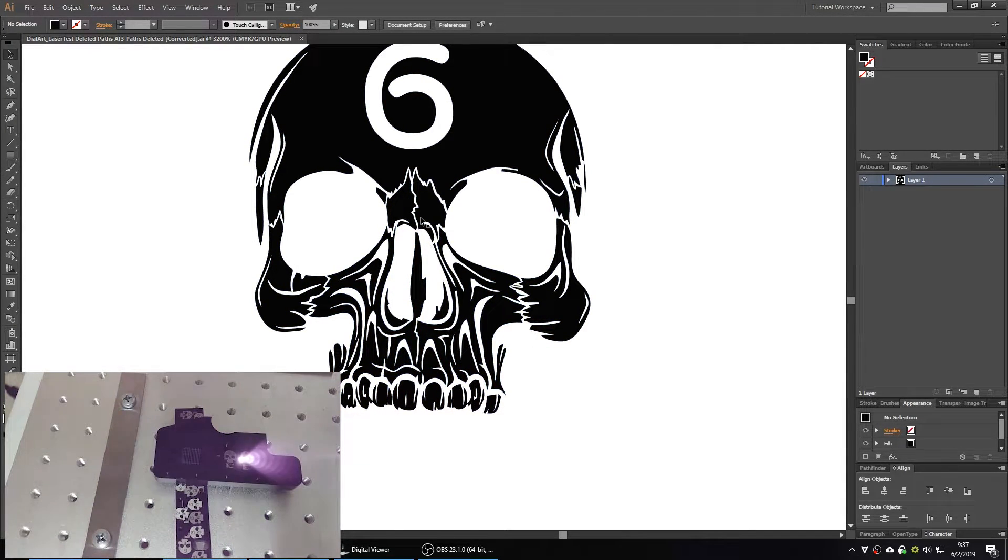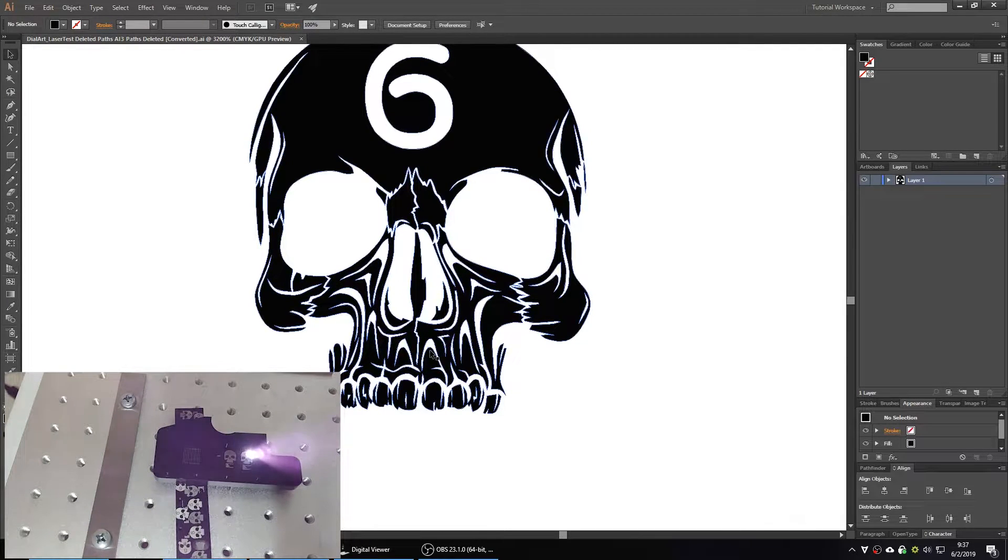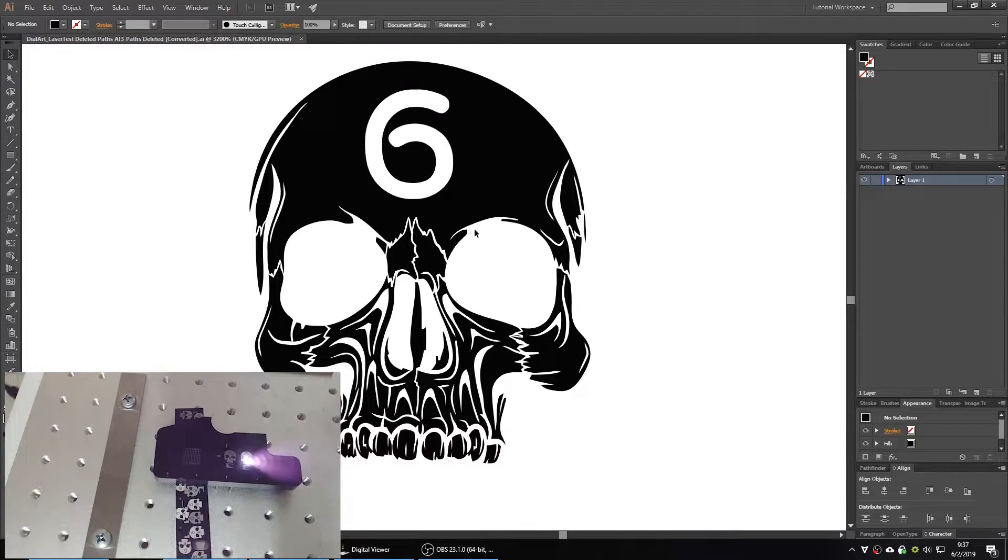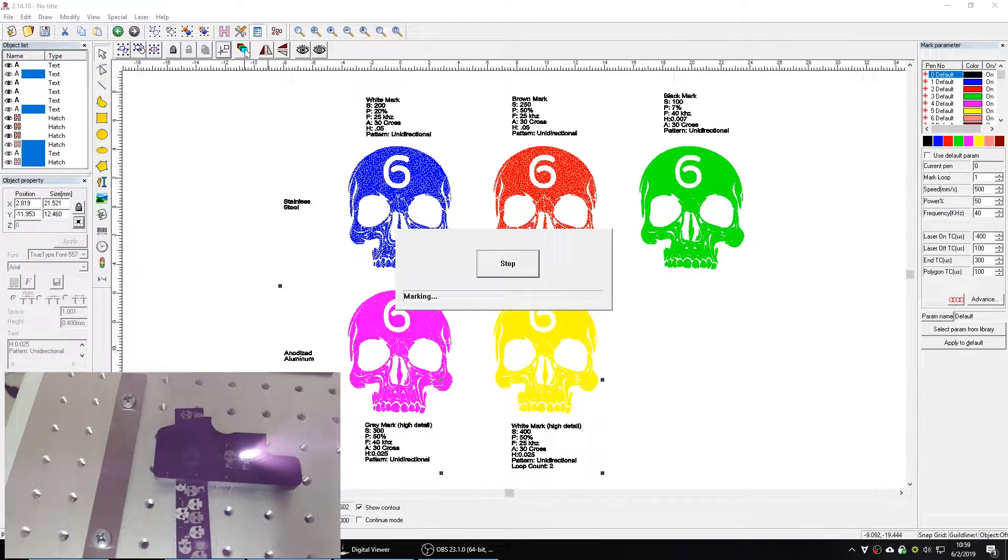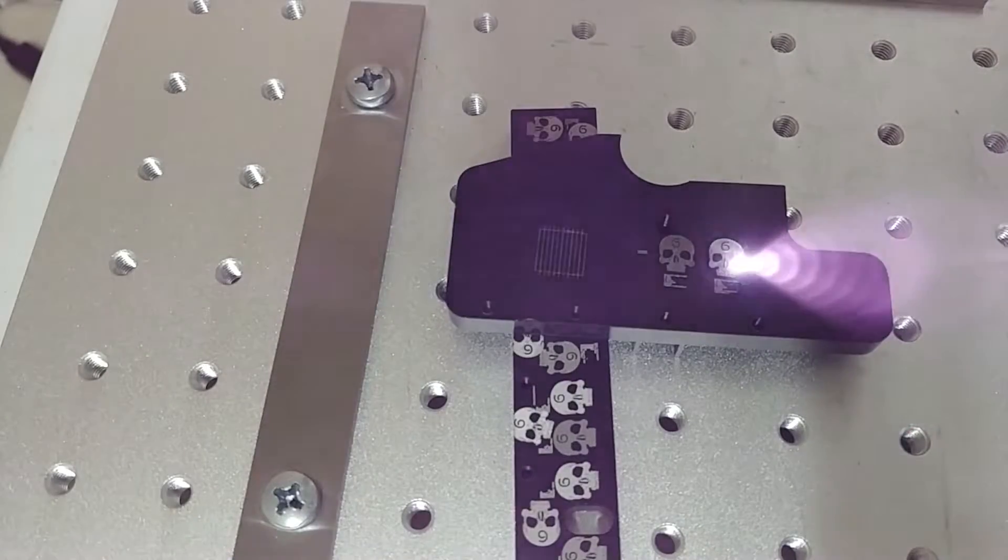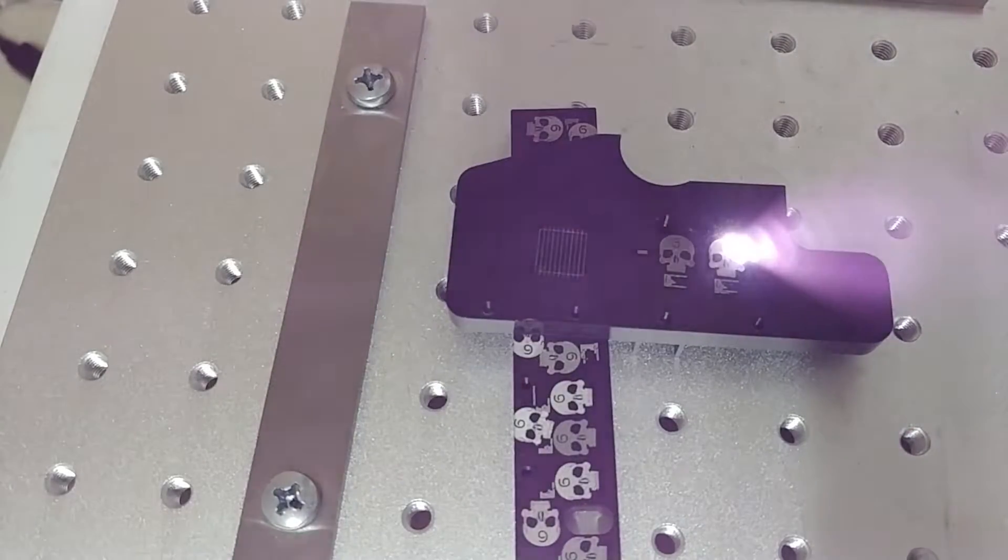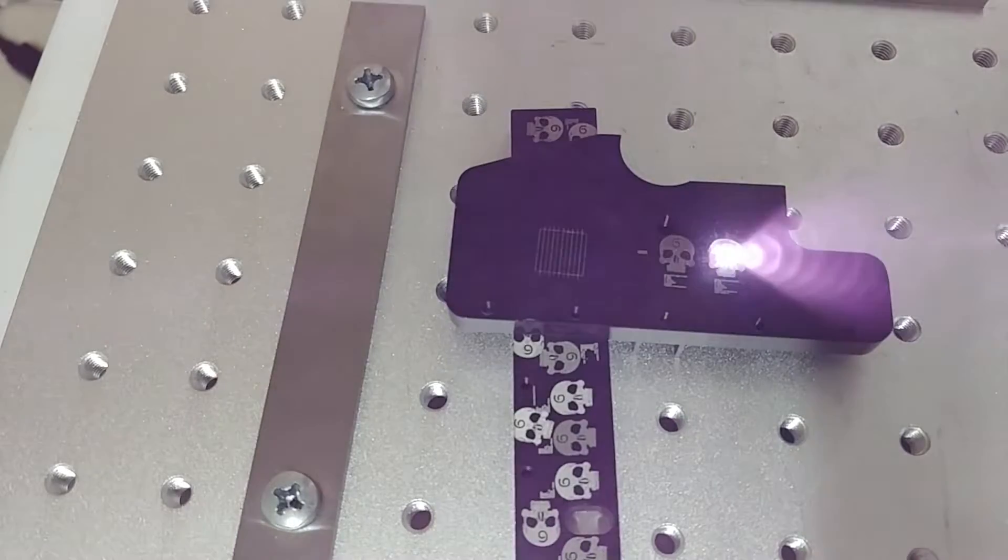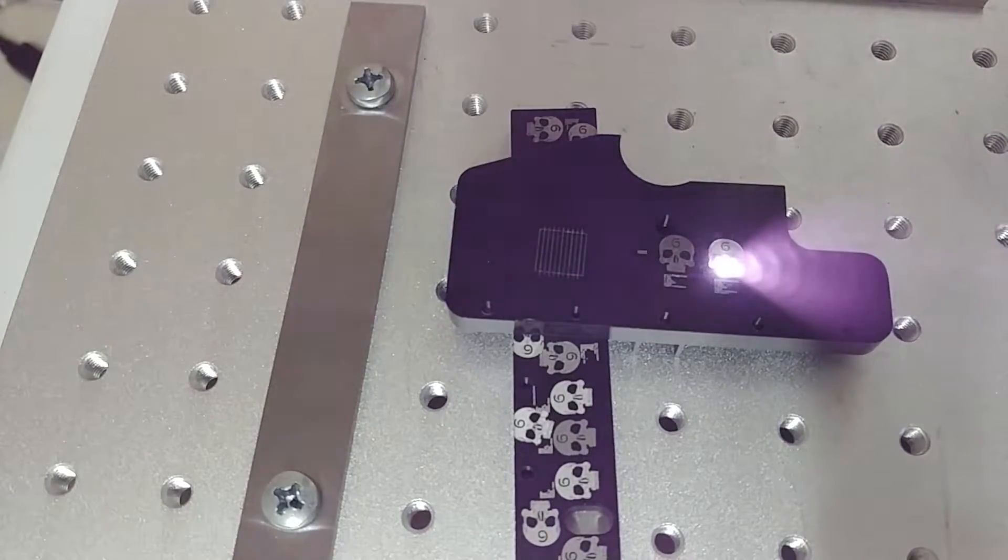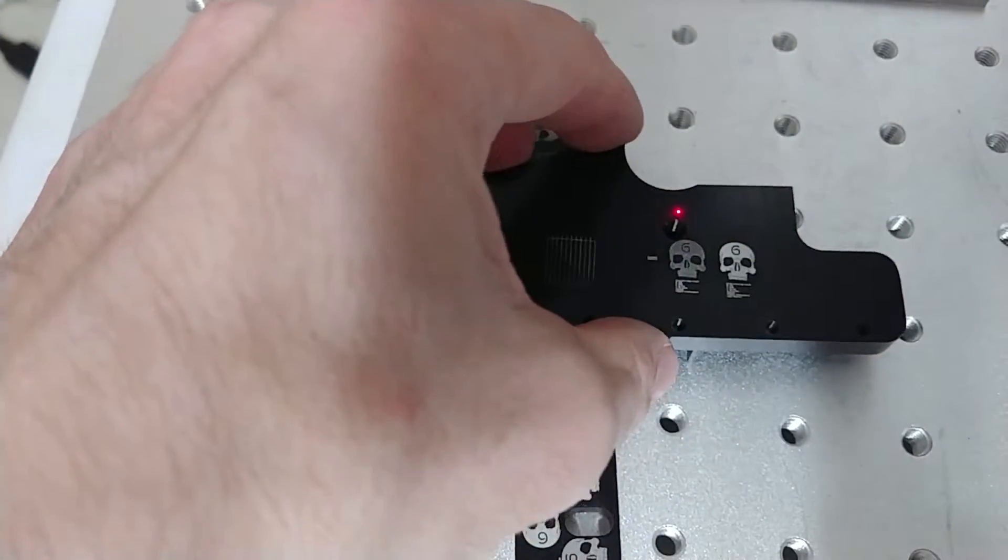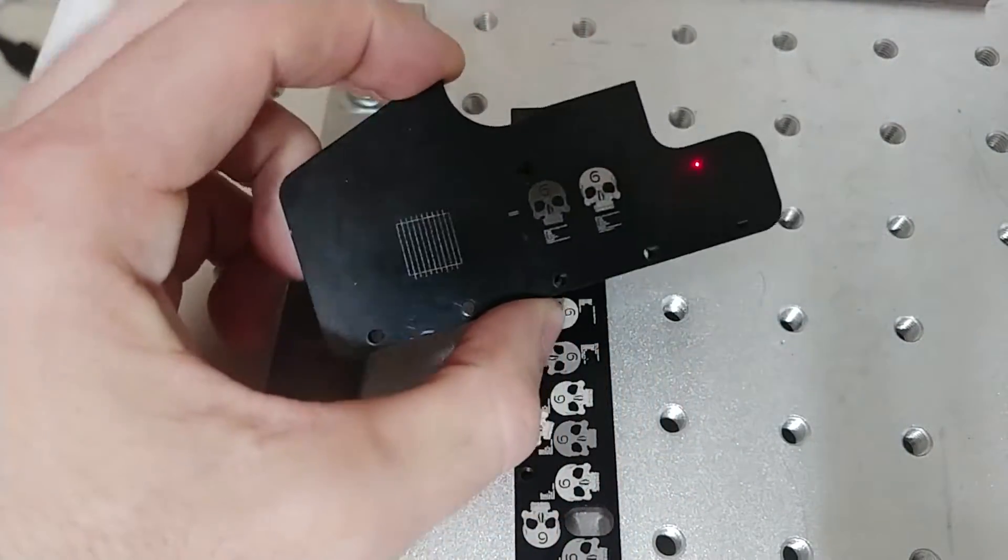I found that when I added a contour it got a little bit worse. When the power was too high, it got considerably worse. When I moved too fast, I set the speed above 500, got considerably worse again. I set the speed too slow, I would end up having kind of a blur of the detail. It would be very filled but the detail would just be lost. If the frequency was too high, often times it didn't fill completely, and the frequency does seem to be what you want to tweak if you want to get the gray mark instead of the white mark.